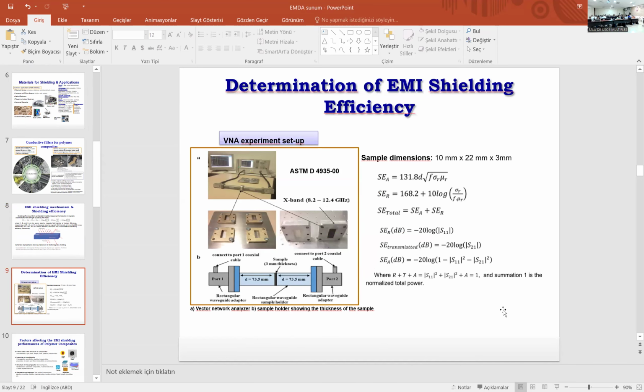Here you can see a vector network analyzer that operates according to the coaxial transmission line method for EMI shielding measurements. In this method, it is possible to resolve separately the shielding effectiveness due to absorption, transmission, and reflection. In addition to the coaxial transmission line method, open field and shield box methods are also used to evaluate EMI shielding effectiveness. The vector network analyzer detects the complex scattering parameters, which we call the S parameters. Based on these parameters, information about the permittivity, permeability, as well as the EMI shielding efficiency can be obtained using suitable algorithms, models, or iterative methods.